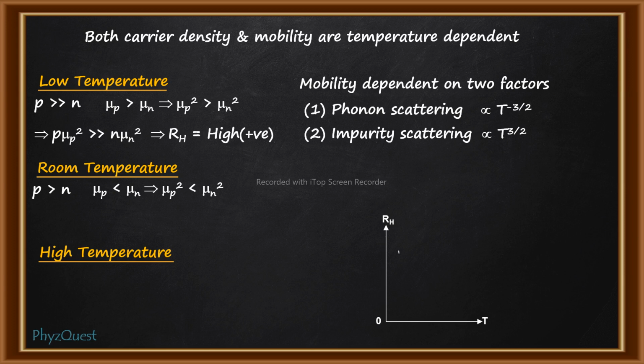And here already we have p greater than n, but mu p square is less than mu n square. So when we take the product, p mu p square will be almost the same as n mu n square. Therefore we can say that the Hall coefficient will be almost 0. So in the plot, when the temperature is raised from low temperature to room temperature, the Hall coefficient will drop from a higher value to 0. Now let's talk about the high temperature range.